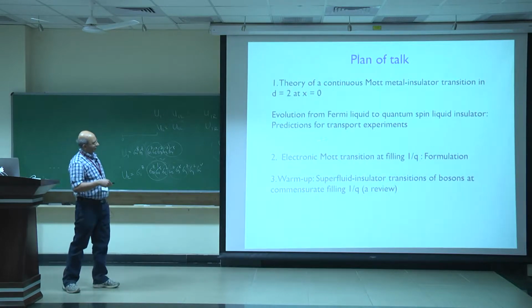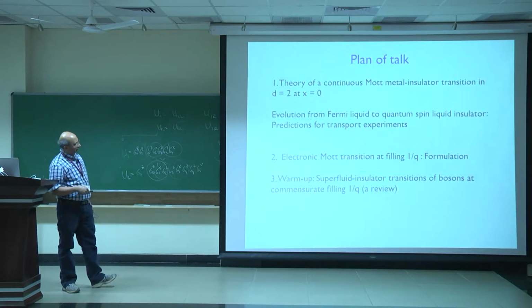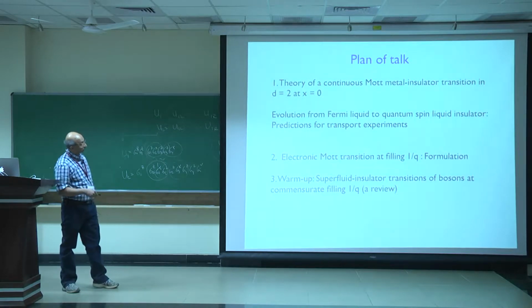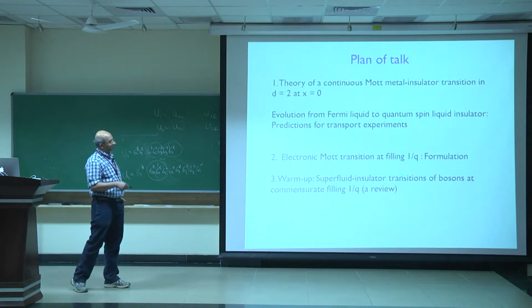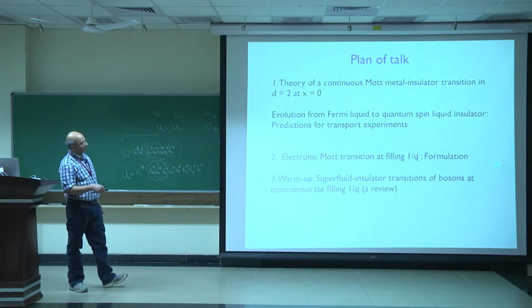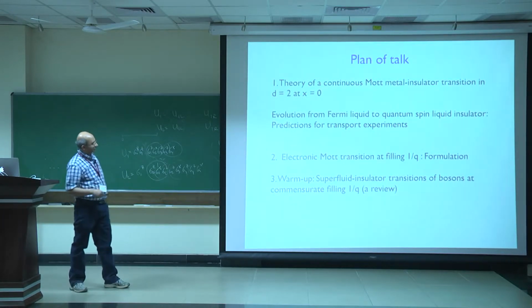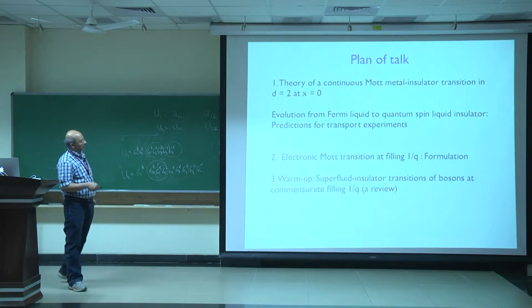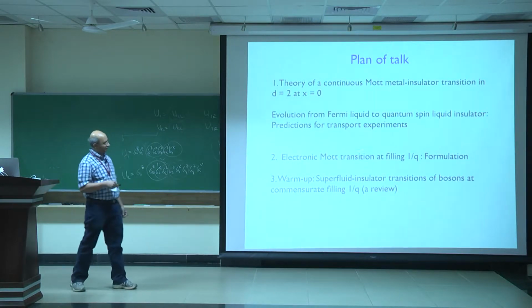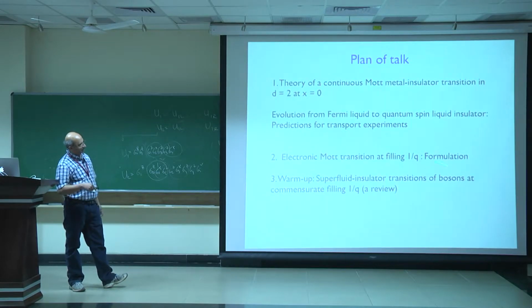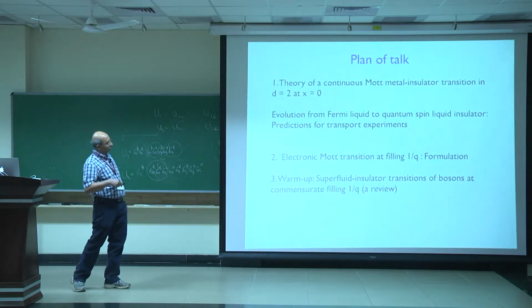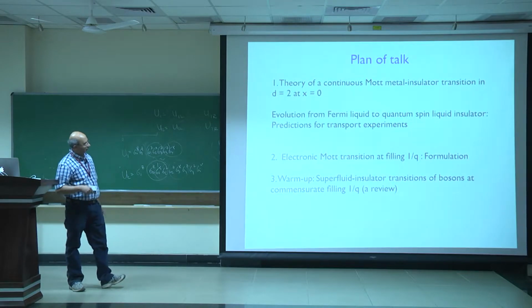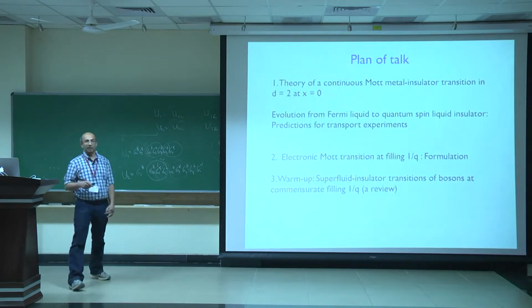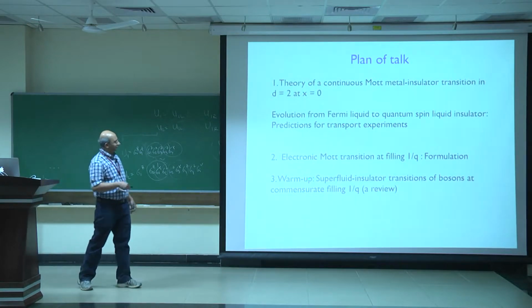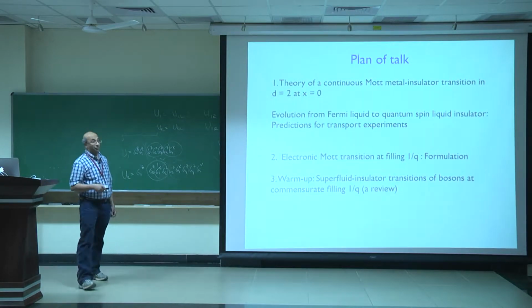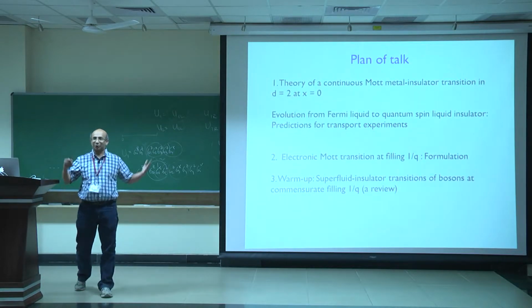And then I'll turn my attention to Mott transitions at commensurate filling. Actually, the filling will be 1 minus 1/q, that's a typo. I'll provide a formulation of this transition and take some initial steps towards doing something with that formulation by warming up, by reviewing the results on a simpler problem of the superfluid insulator transition of bosons at commensurate filling. Okay? And so the talk will end somewhere halfway because that's all I know so far.